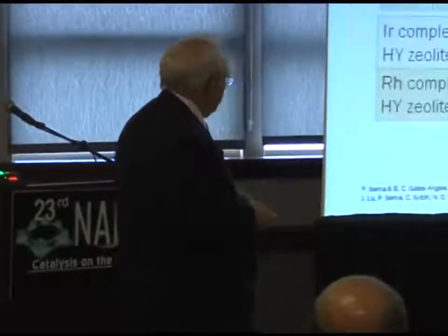So I want to take a little bit of an aside now because I need this to go further. What we found in investigating those catalysts was that the hydroxyl groups on the zeolite Y support are playing an important role in the dimerization catalysis. Just one experiment: we have the catalyst deuterated and then introduce ethylene, and we see right away that the OD stretch intensity declines because the olefins are being bonded to it, and then the dimerization catalysis kicks in. Okay, so there's more evidence, but I don't have time for it.